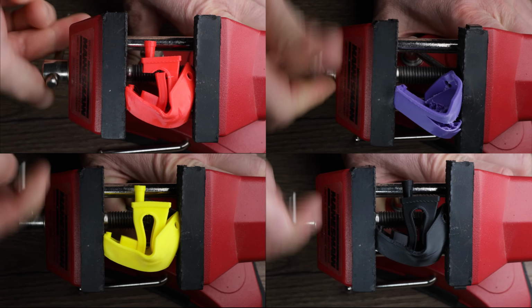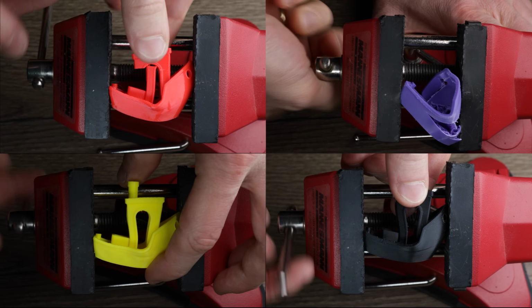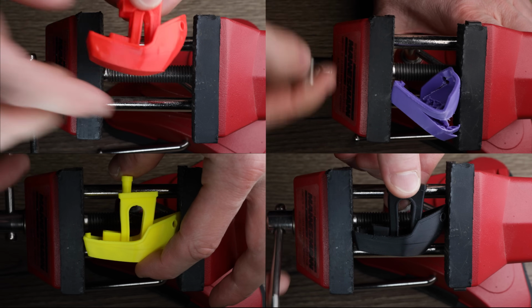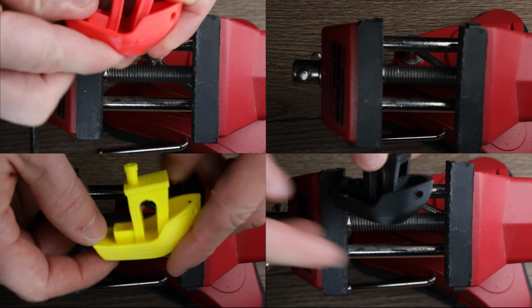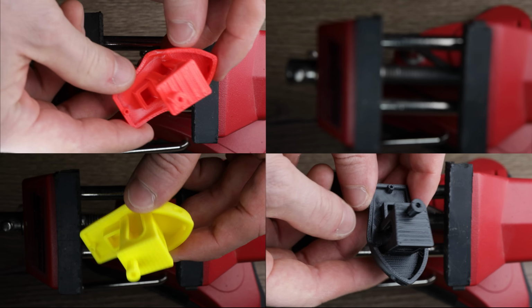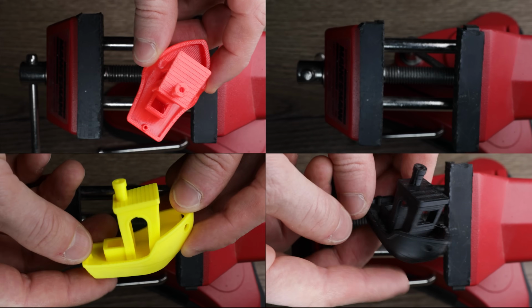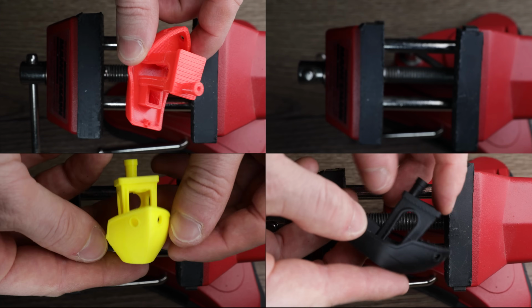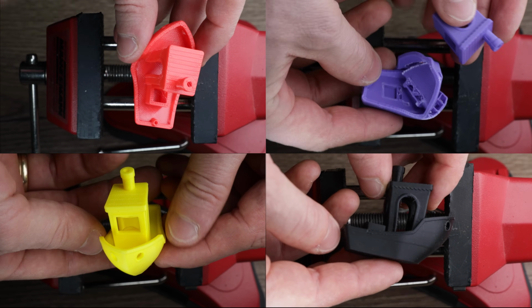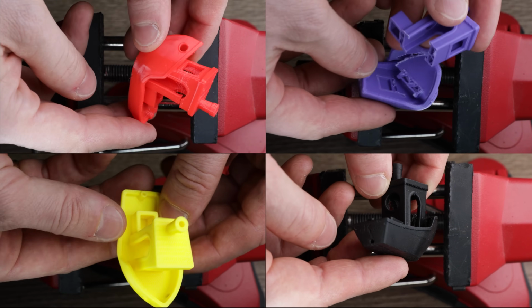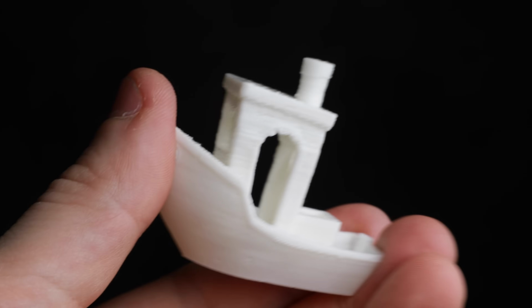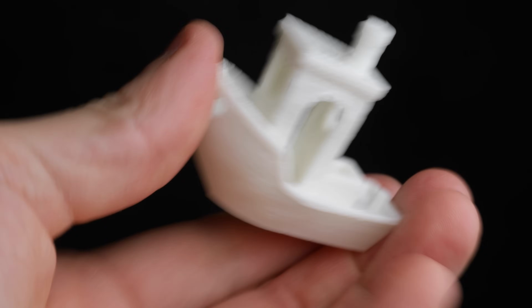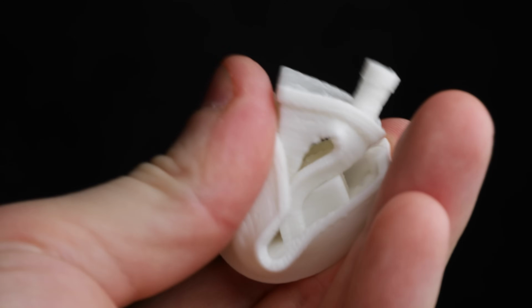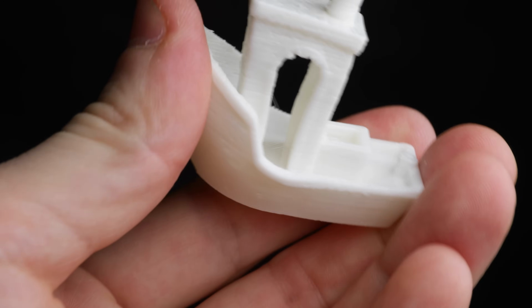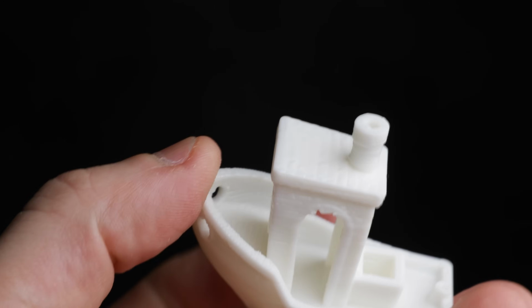But here's the interesting part. Once I loosen the vise, the TPU for AMS benchy almost returns to its original shape. Sure, the cabin broke off and there is a slight deformation on the railing, but compared to the scattered PLA benchy, this difference is striking. I left out the TPU 60E benchy for this test. After all, as you saw earlier, that one is so soft you can practically knead it with your fingers.